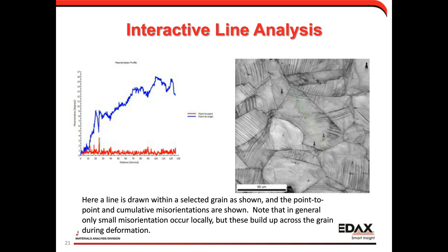We can draw what we call a point-to-point misorientation, which shows as we go along that line from one point to the other what misorientation is present. You can see that's the red distribution there. And in general, that's very low. There's small misorientations occurring within the grain. But if we look at the point-to-origin distribution, which is the blue line there, you'll see that those small misorientations are cumulatively building up into large rotations. So we can see how that total grain deforms spatially while still measuring small misorientations on a point-to-point nature.